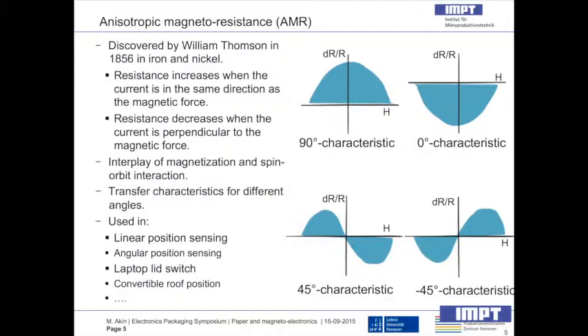And for your convenience, I do have here some transfer characteristics for different angles between electric current and magnetic field, where this transfer characteristic is basically a change in electrical resistance. And you see for the 90-degree characteristic, from the zero magnetic field, with increasing magnetic field, the electrical resistance decreases. The opposite happens for the 0-degree angle, and this is what you see there on the bottom of the slide. What happens if you have a 45-degree or a minus 45-degree angle?